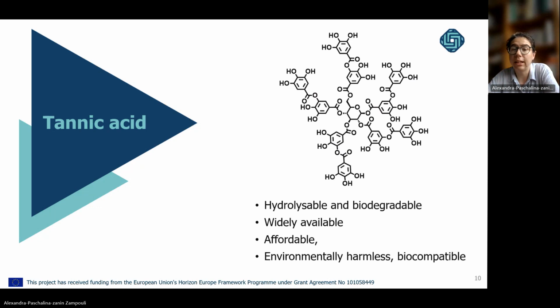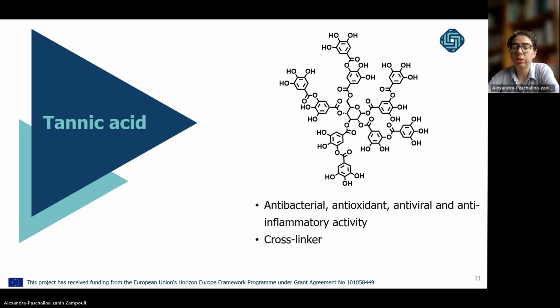So tannic acid is hydrolyzable and biodegradable as an ester. It's widely available, affordable, environmentally harmless, and biocompatible. Also, it has been found to have antibacterial, antioxidant, antiviral, and anti-inflammatory activity. When it comes to polymers and polymer composites, it is used because of its numerous hydroxyl groups. It is often used as a cross-linker, either with natural polymers such as chitosan to improve mechanical properties, or also to cure resins.